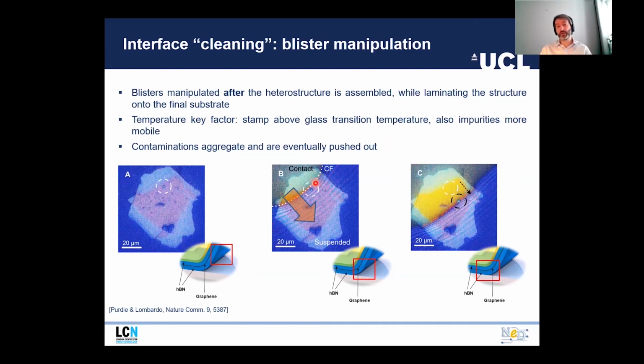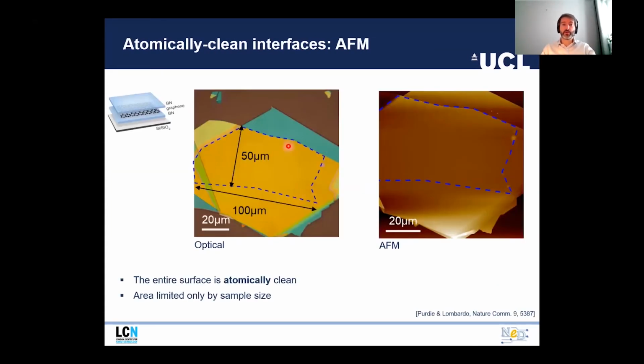As the contact front moves, as you can see in the second picture, it collects all the impurities, which eventually merge together and are pushed out of the heterostructure. So at the end of the process, we end up with a sample which is completely clean of impurities. If you look closely at the AFM picture, there are some impurities just at the edge, because when there is a discontinuity, that acts as a pinning point. But the entire graphene area is completely free of blisters. In other words, we are achieving atomically clean interfaces, limited only by the sample size. And that is very important when we make devices.